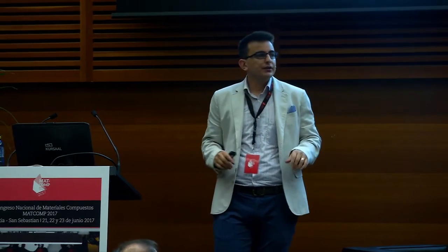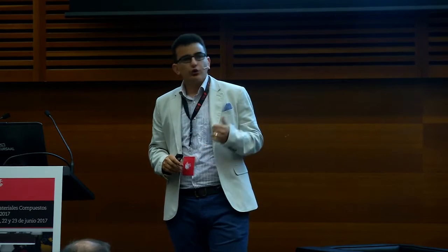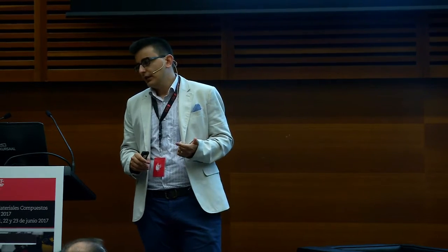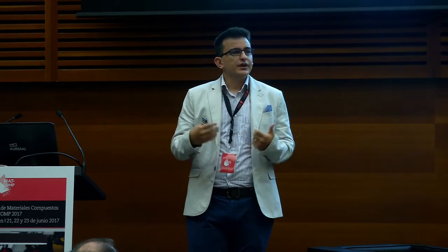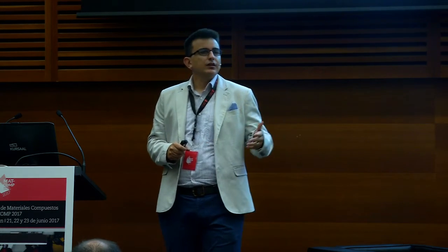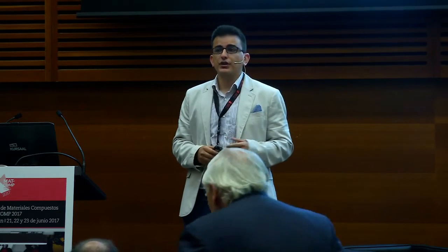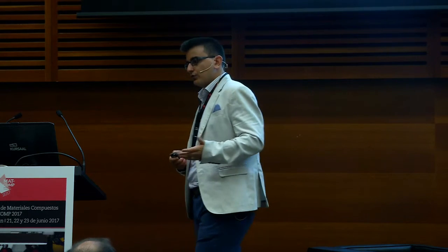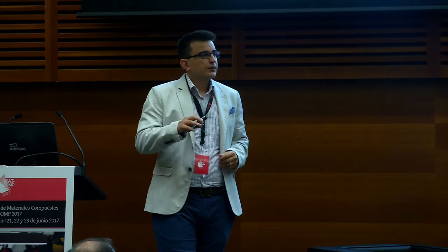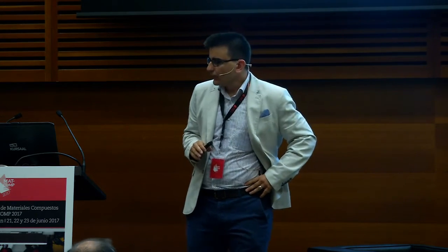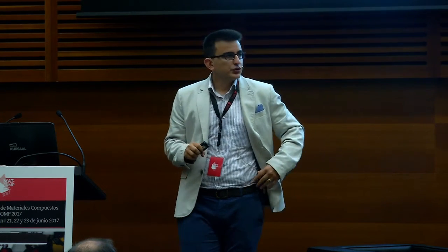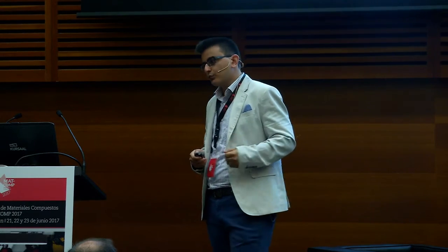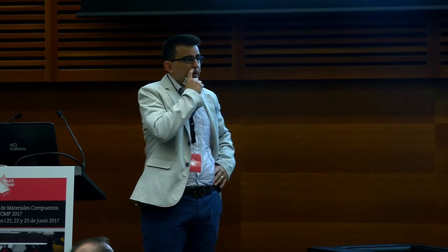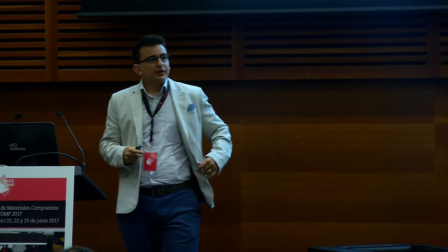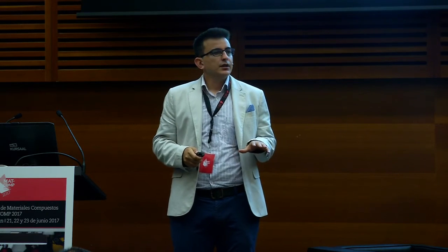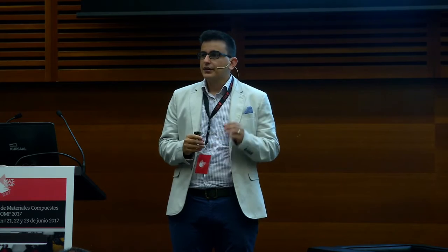So now we have a well-defined process model. We took geometry information, material behavior, and the process parameters into account, and we verified our process model such that we can now use it for process simulations and process control. One option using the process model is controlling the manufacturing inline. So I have here a block of model-based inline process control. So we are very active in this field, not for pultrusion, but for laser-assisted tape winding process, in which we are developing a physics-based process model, and our aim is to calculate the nip point temperature.